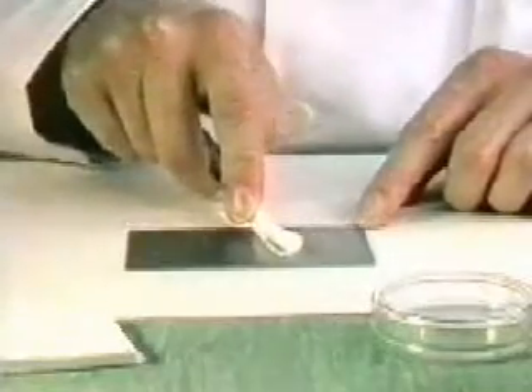Then a new pad is placed to the right of the mounting point within the area just cleaned and then drawn to the outer left. This procedure is intended to remove any final contamination from the critical region. The bonding process should now follow immediately after this cleaning.